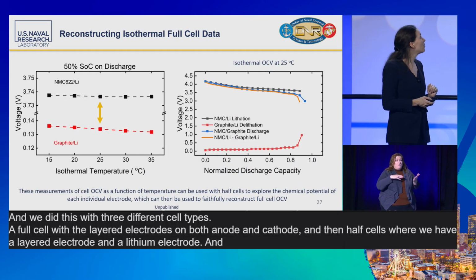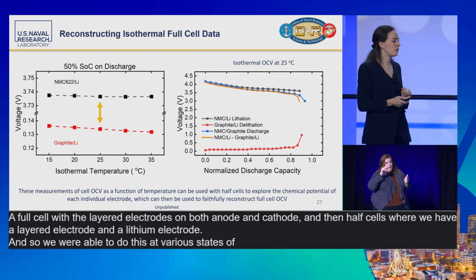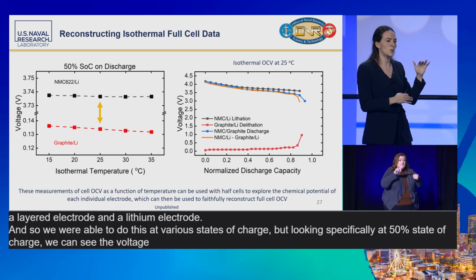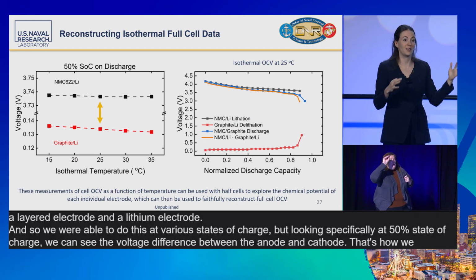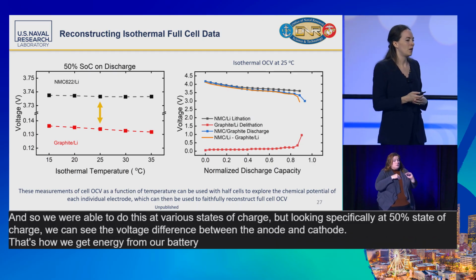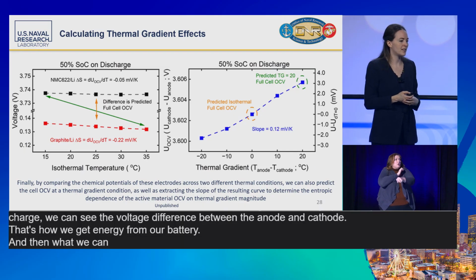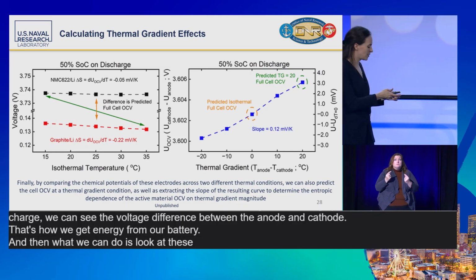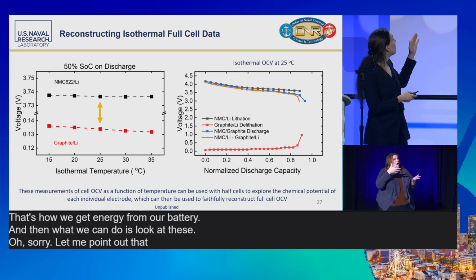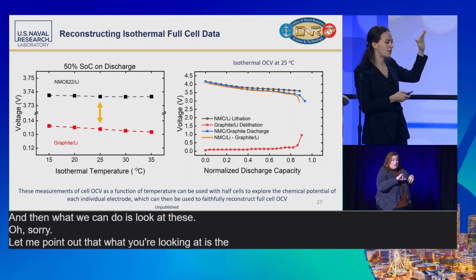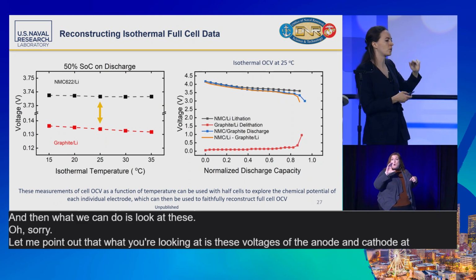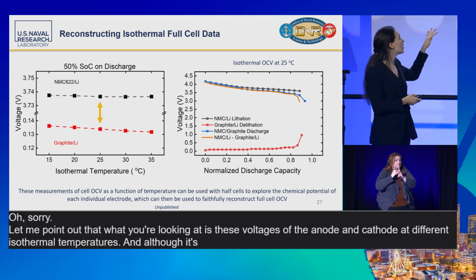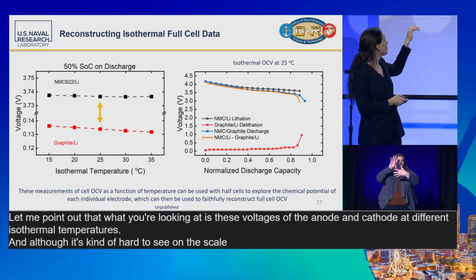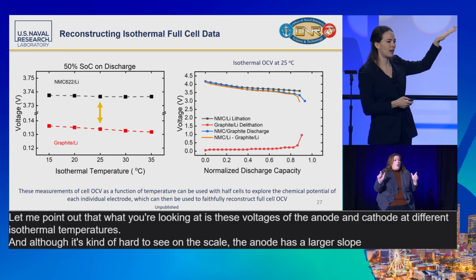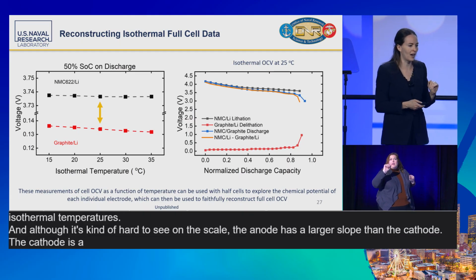And so we were able to do this at various states of charge, but looking specifically at 50% state of charge, we can see the voltage difference between the anode and cathode. That's how we get energy from our battery. And then let me point out that what you're looking at is these voltages of the anode and cathode at different isothermal temperatures. And although it's kind of hard to see on this scale, the anode has a larger slope than the cathode. This cathode is a more flat line there.